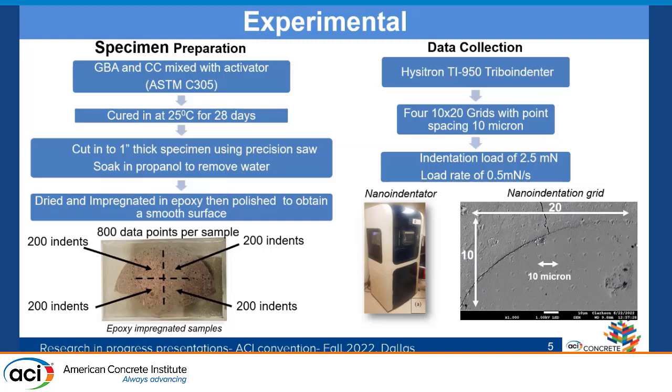I followed a 10 by 20 grid pattern with a spacing of 10 microns between nanoindents. And the indentation load I used was 2.5 millinewtons.